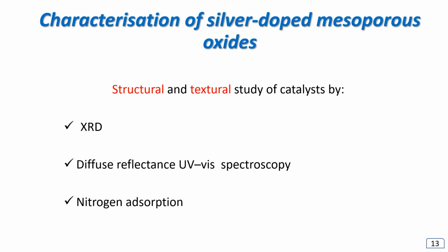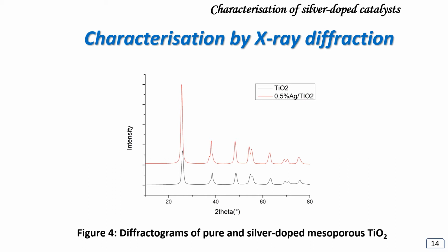We studied the structural and textural evolution of mesoporous oxide using X-ray diffraction, UV visible diffuse reflection, and nitrogen adsorption. Diffractograms of pure and silver-doped titania show lines attributed to the anatase phase of titania and that this structure is maintained after silver doping. We note that for silver contents of 0.5%, the diffraction lines are shifted toward the lower 2 theta, which can be explained by the incorporation of the larger Ag+ cations into the Ti octahedral positions. Note also that the silver-doped materials are better crystallized than pure titania, suggesting that the silver species catalyze the recrystallization of the oxide during